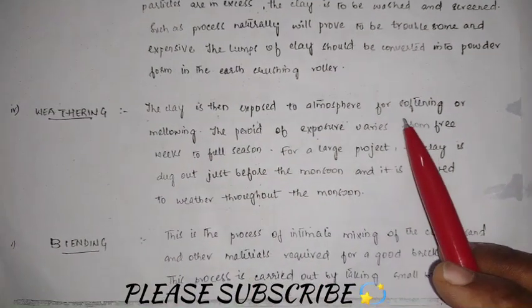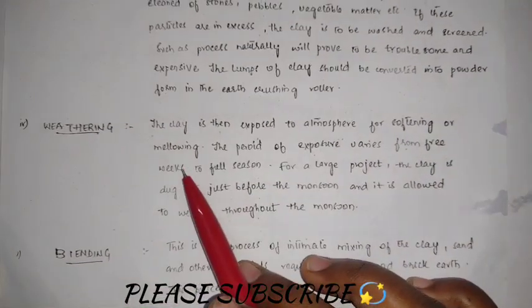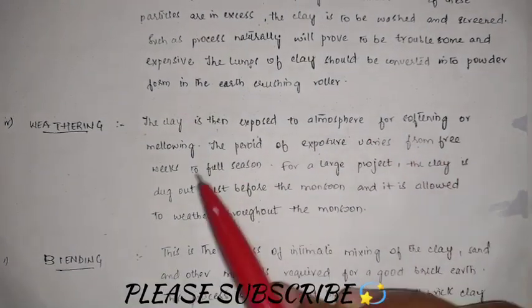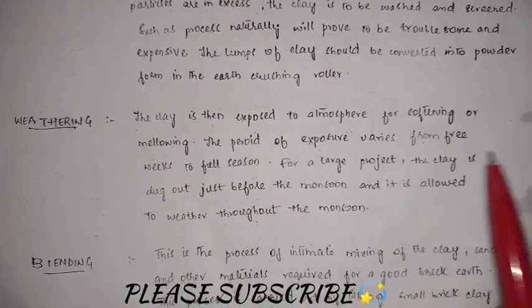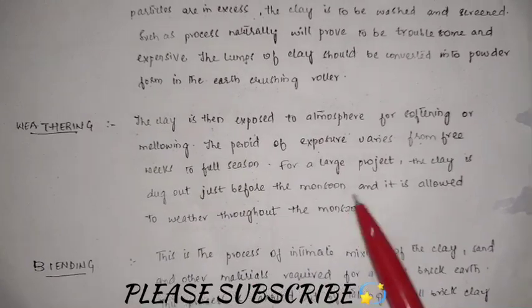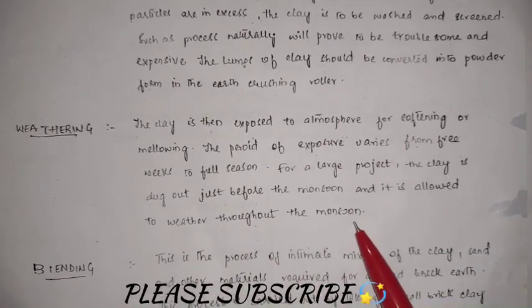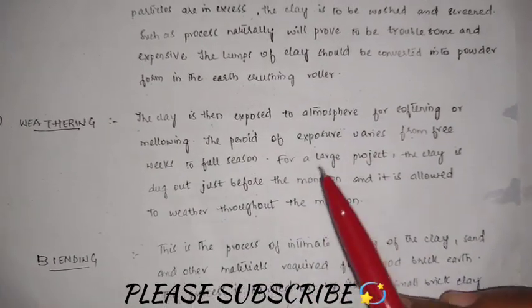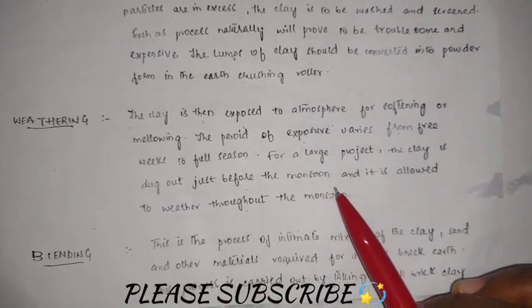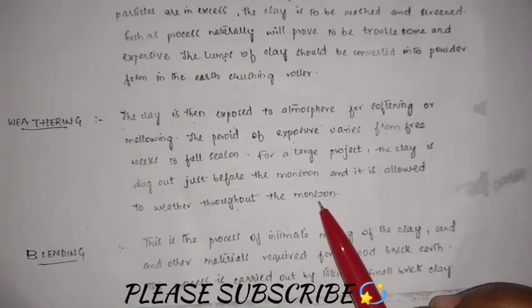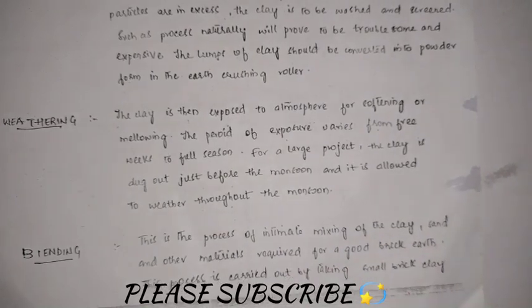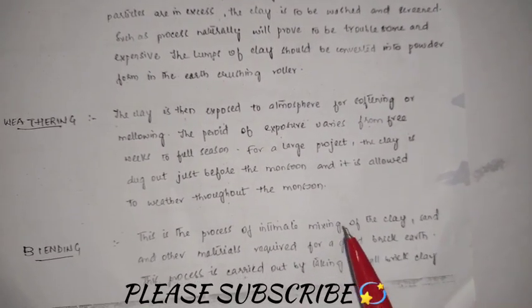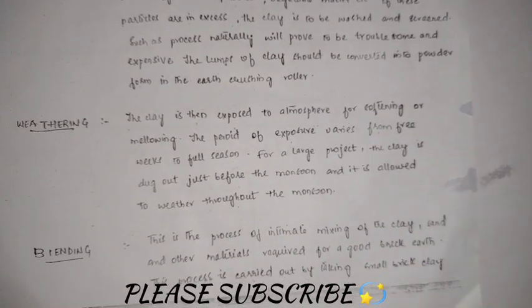The clay is then exposed to atmosphere for softening or mellowing. The period of exposure varies from few weeks to full season. For a large project, the clay is dug out just before the monsoon and it is allowed to weather throughout the monsoon. So in this case, the loose soil thus obtained is cleaned thoroughly and exposed to weather for softening. The period of weathering varies from few weeks to full season. So it depends upon the type of soil and the time available for us to do the weathering.